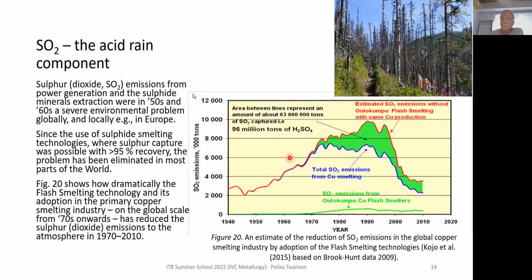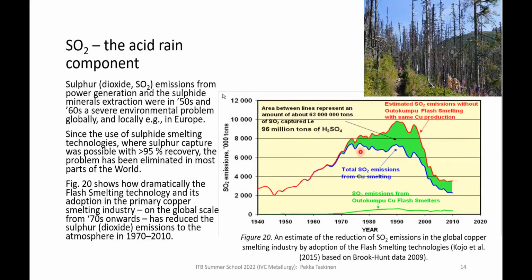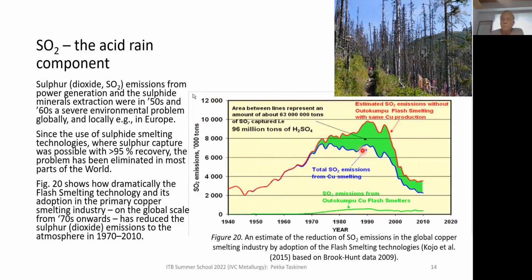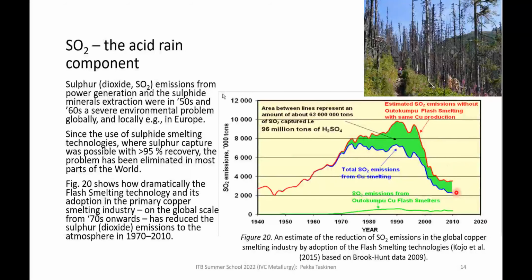So in total, in this period of time from early 70s till mid 90s, some probably 30 or 40 copper smelters were erected with flash smelting technology, and this makes the difference. So the downward slope is due to shutting down typically reverbs and blast furnaces.